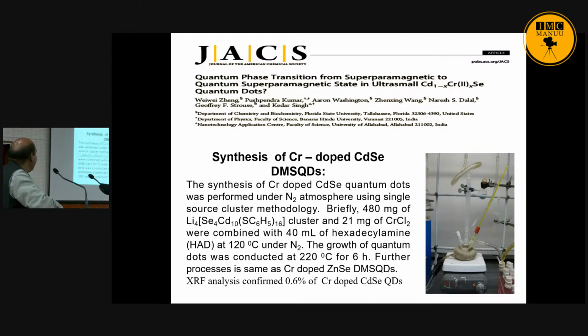This is 40 ml hexadecylamine, known as HDA, at 120 degrees centigrade under nitrogen. This is the system here, with nitrogen flowing, in a 3-neck flask, and we are stirring here. The whole reaction is under nitrogen. The reaction is conducted at 220 degrees for 6 hours. Then we dope 0.6% chromium in the CdSe quantum dot.